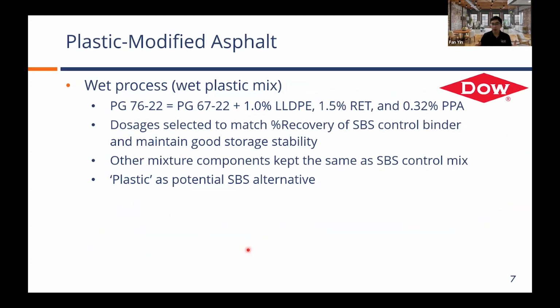So with that being said, the separation issue is a big challenge for the wet process. In order to address that issue, at least in this specific formulation, we have to do some formulation work to make sure those two materials like each other, if you will. The approach we took was working with Dow Chemicals to introduce a terpolymer into the system so that the terpolymer can hold hands, almost, with one side to the asphalt binder and the other side to the recycled plastic, saying, hey guys, let's work together to make it work.